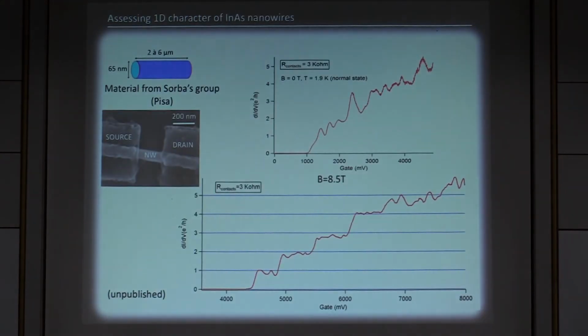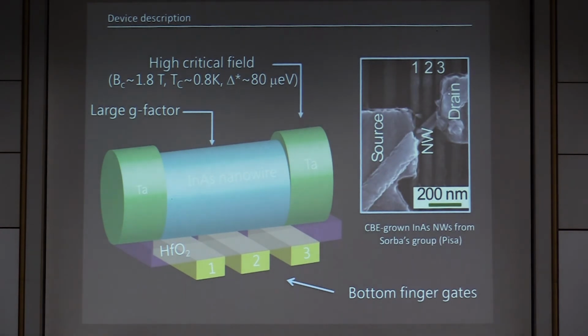So it's kind of convenient, if you search for one-dimensional effects, you want to be in the most favorable situation, so have channels that are as short as possible. So these are some other data, not published, obtained with the indium arsenide nanowire. Again, the channel is around 200 nanometers, and you see quantization at multiples of e²/h at high magnetic fields once again.